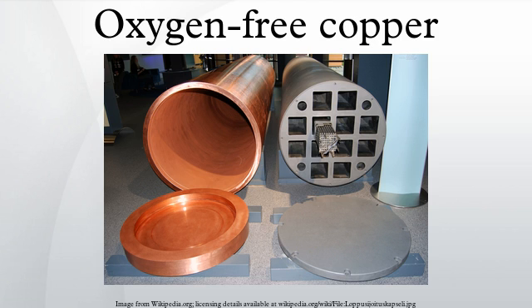The high-end speaker wire industry markets oxygen-free copper as having enhanced conductivity or other electrical properties advantageous to audio signal transmission. However, conductivity specifications for common C11000 electrolytic tough pitch and higher-cost C10200 oxygen-free coppers are identical. The much more expensive C10100, with silver impurities removed and oxygen reduced to 0.0005%, has only a 1% higher conductivity, which is not considered significant in audio applications. OFC is nevertheless sold for both audio and video signals in audio playback systems and home cinema.